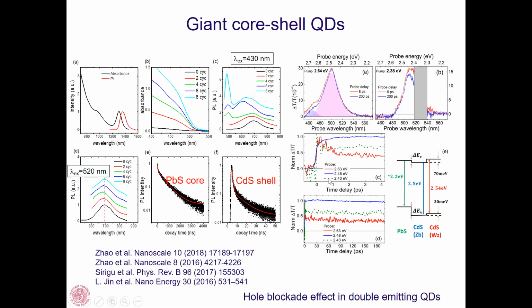Then, by applying ultra-fast pump-probe spectroscopy at Politecnico di Milano, so I'm not an expert in this, the outcome of these measurements is that we were able to draft an electronic structure for our materials in which the lead sulfide is surrounded by a thin zinc blende shell of cadmium sulfide, which acts as a blockade layer for holes produced in the external shell, preventing them from recombining into the core and originating the double emission.